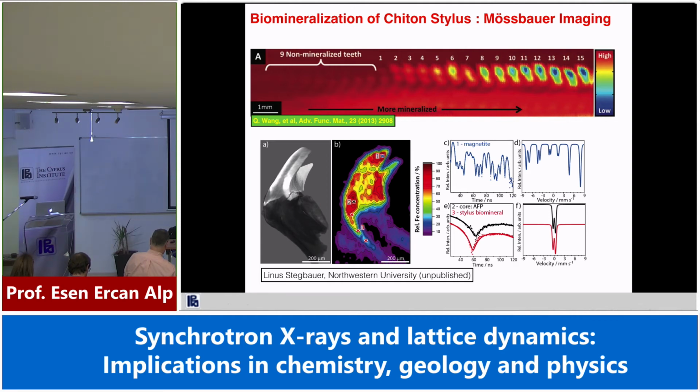Other questions, comments? The most common method is restricted, right, to some isotopes. That's right. What do you do about the ones you don't know? The ones that you cannot analyze? You just cannot. We are lucky that iron was a gift. I wish germanium or silicon had a Mössbauer transition, but it does not. So if you have a sample with an isotope that doesn't, I'm developing a new method called time domain interferometry to study those samples that do not include Mössbauer isotopes, using the Mössbauer transition and highly monochromatic beams.